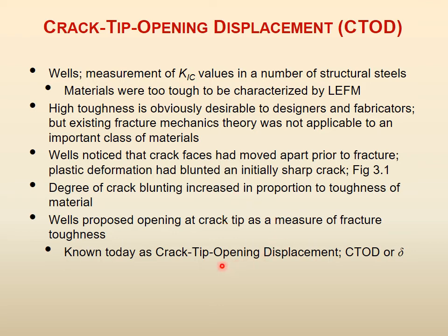How round does it become? A little round with a small radius or a big round with a big radius? If it is more tough, there the roundness will be more. So he said, let us measure this opening of the crack tip and use this as a measure of the fracture toughness of these type of materials. So today it is known as crack tip opening displacement, CTOD, or this delta for opening displacement.